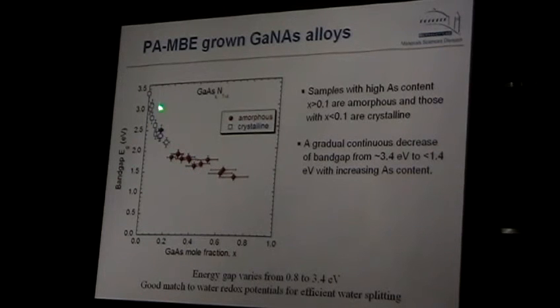And we have a really interesting system now, which is still open, because as you see, we are again changing the gap from 3.4 going to a very low gap, and in fact the lowest gap we observed was 0.7. So we almost have the same system as we had for gallium nitride, that we can cover the whole solar spectrum. The question is how amorphous will work. In this case it is still open.